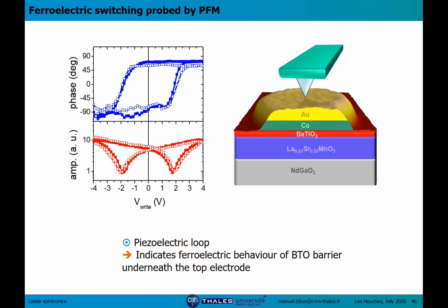So this is the conductive tip, and first we can check that the barium titanate in the tunnel device is ferroelectric. These are piezo response measurements, piezo response loops that mimic the polarization loop and indicate that ferroelectricity is maintained, is preserved when the barium titanate is encapsulated in the LSMO and cobalt electrodes.